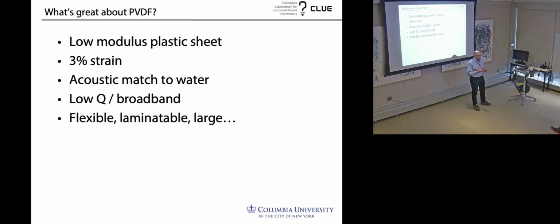And so even though the D33, or the transduction of strain to charge, is not that great, it's only about 1/10 of what you have for a ceramic piezoelectric material, the transduction of force to charge, or G33, is actually excellent. It's one of the best that's known. So that low modulus is nice.